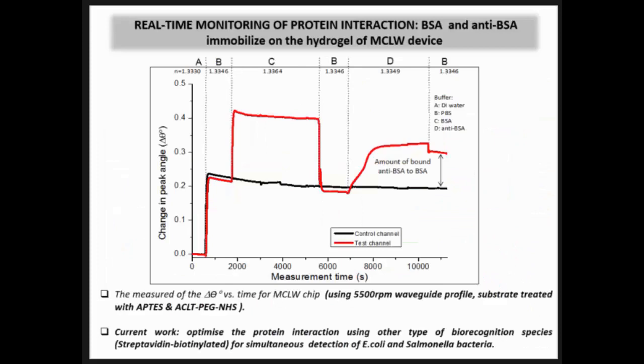So in order to study the stability, we probe the protein interaction. In here is BSA and anti-BSA immobilization on the hydrogel. We have one control channel here, and this is the test channel. This is where we keep PBS so that we can monitor it as a reference, and this is where we change from water. Then we move to PBS and PBS with BSA, and then we wash away the remaining BSA that did not bind with the hydrogel. Then we flow the anti-BSA, and you see that there is a change here when we wash away with water. If there is any binding, it will not shift to the original position, but it just sticks here.